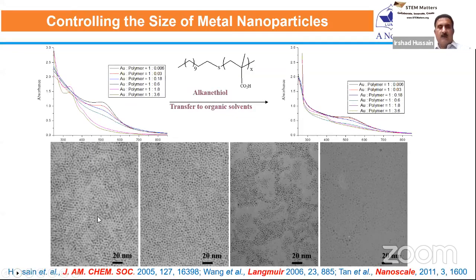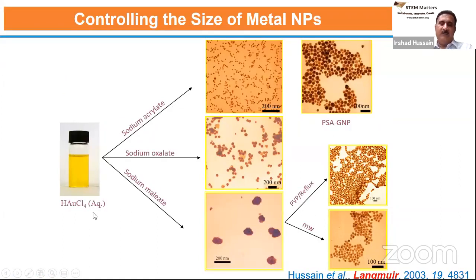Okay. In addition to these smaller particles, we also developed various strategies by which, simply using weak reducing agents like sodium acrylate, sodium oxalate, or sodium maleate, we were able to prepare gold particles that range in size from 10 to about 100 nanometer. So basically, we developed all these strategies to prepare gold nanoparticles that range in size from 1 to 100 nanometer. And depending on their size, they have different optical properties.